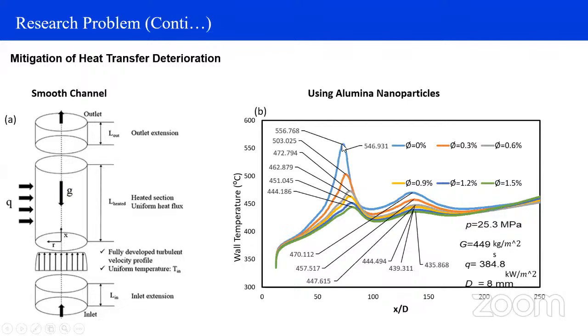So if we decrease the peak, it is called mitigation. Our main objective is to reduce the deterioration inside the nuclear reactor. We use different concentrations of nanoparticles. First we try 0% nanoparticles, so we draw a result without nanoparticles. Then we include 0.3% concentration of nanoparticles inside our base fluid, then 0.6%, 0.9%, 1.2% and 1.5%. And we observe different outcomes in temperature profiles.